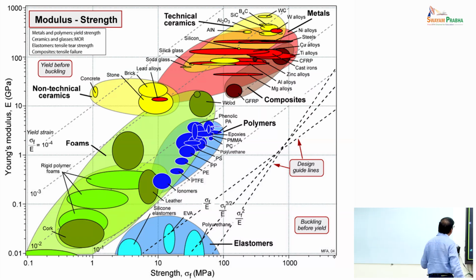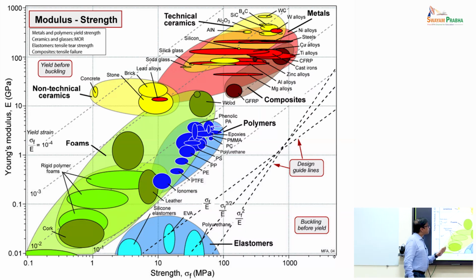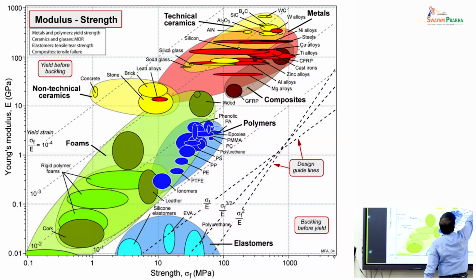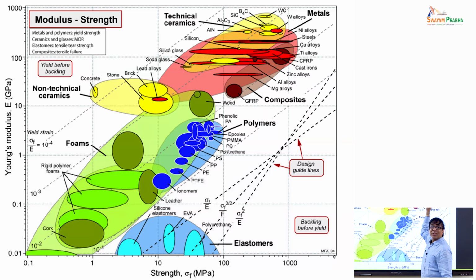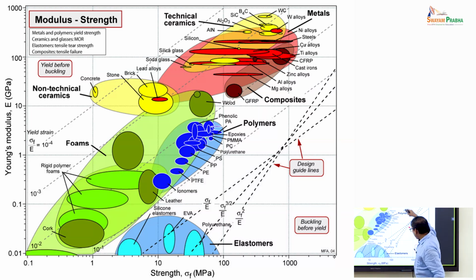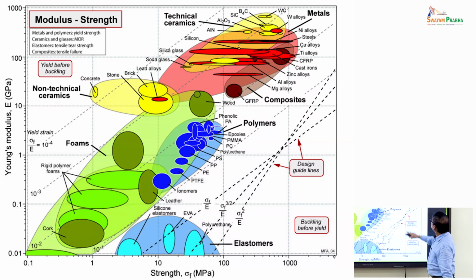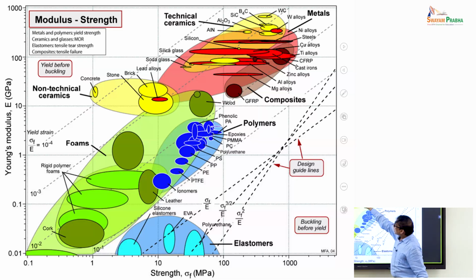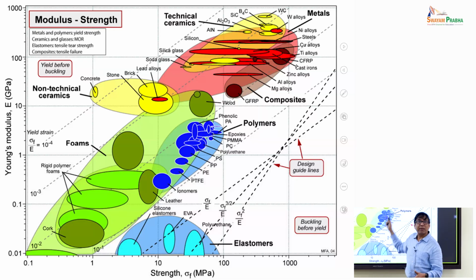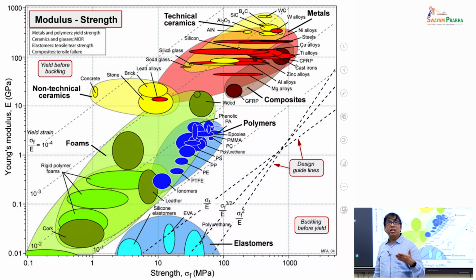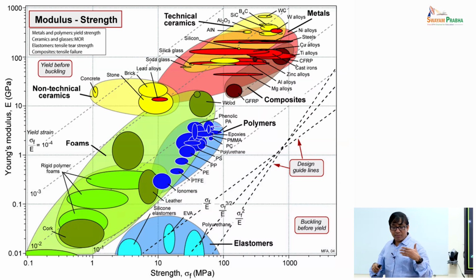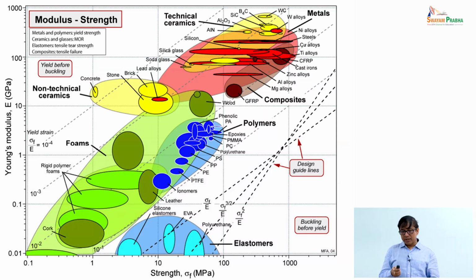And if you look at some of the polymer based samples, they are on the other side of the spectrum. So we are always dealing with materials of this level, which means when you are talking about strengths close to a gigapascal, and Young's modulus in the order of several gigapascals, then unless you have the ability to measure them accurately, you fail. So that is the reason why you need to have a rough idea of its strength and Young's modulus, so that you can deal with such kinds of machines.